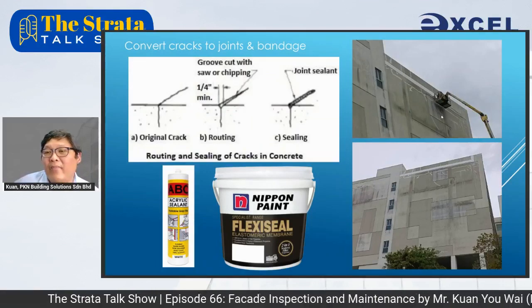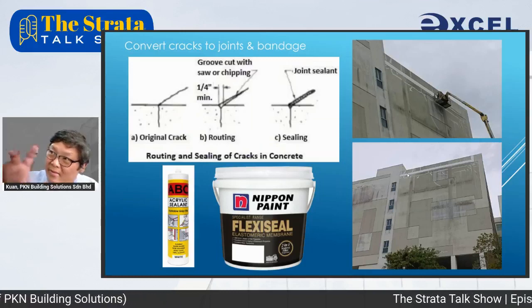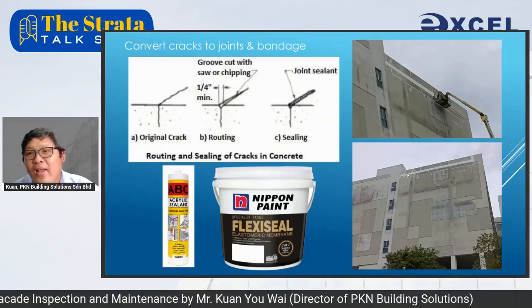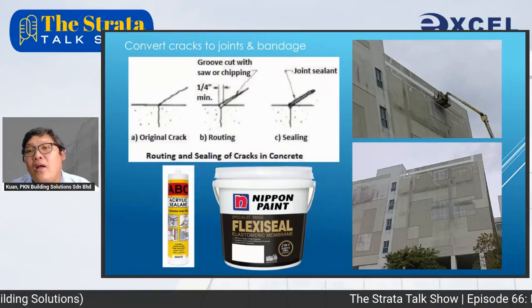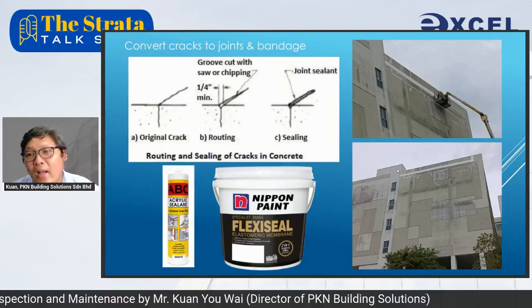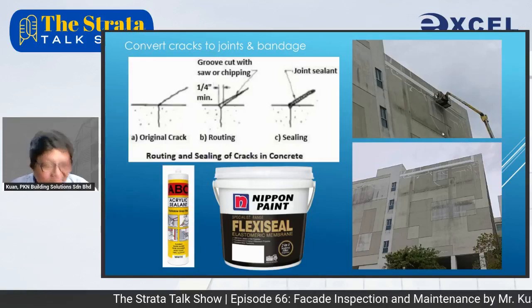Meantime, I also discovered that using single ply membrane to bandage the horizontal crack line under the flat roof is very effective, because I actually removed the falling concrete pieces and debris. I removed it, not even patching it back. Instead, I used single ply membrane and installed stainless steel brackets on top and below so that no water can seep through. Of course, I need to seal it with a high performance sealant. In this case, this is a once-and-for-all durable and permanent type of solution, because it's very expensive to control the heat from the top. So I make the area that is subjected to expansion and contraction under the flat roof elastic forever. So it can move and it will still be watertight.